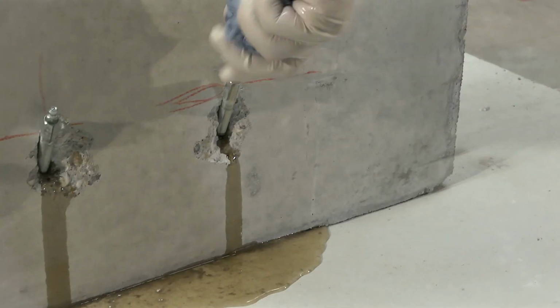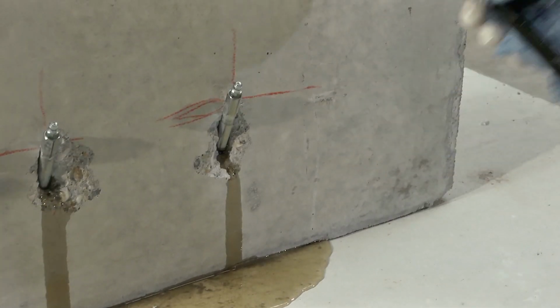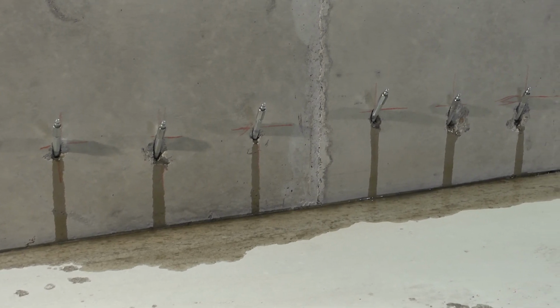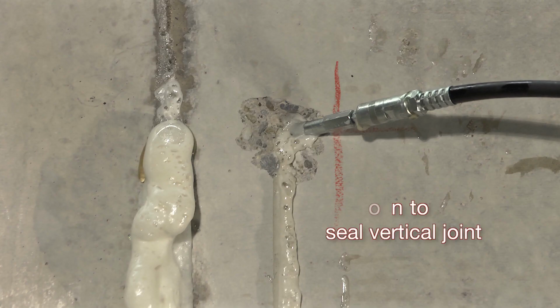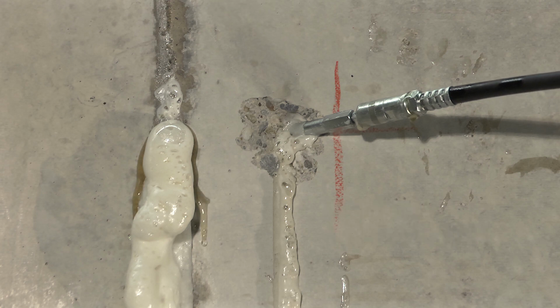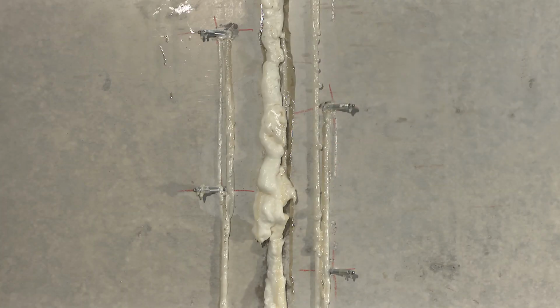Before the pot life expires, which is approximately 100 minutes for Intectant Plus, regrout the crack another time and, if required, several times using the already described sequence in order to achieve complete crack filling.